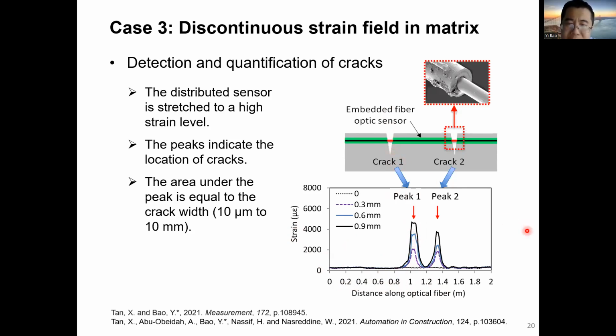And we did a lot of experiments and we found that we could even quantify or estimate the crack opening width because theoretically, there's a relationship between strain and deformation, right? If we do the integration within this range, we could quantify the crack opening width. And we found that we could quantify the crack opening width within a very large range. This work has been reported in these two papers.